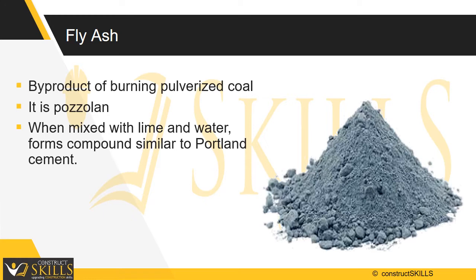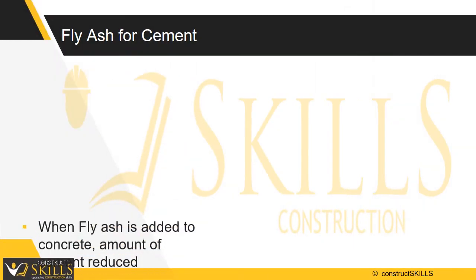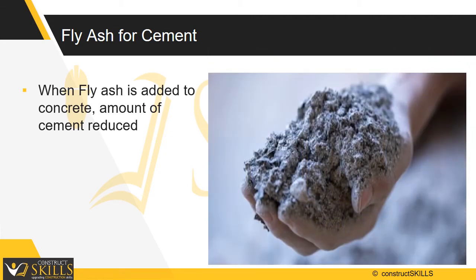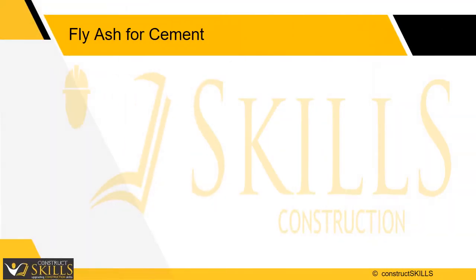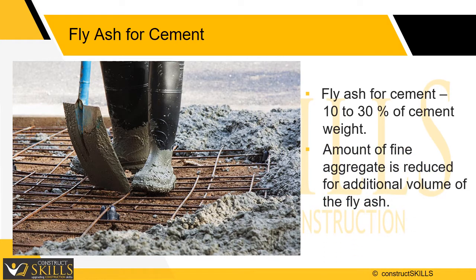The use of fly ash improves concrete performance in both the fresh and hardened state. When used in concrete mixes, fly ash improves the strength and reduces segregation of the concrete and makes it easier to pump. When fly ash is added to concrete, the amount of cement may be reduced. The amount of replacement depends upon the design consultant. The rate of substitution of fly ash for cement is typically specified at 10 to 30 percent of total cement weight. Accordingly, the amount of fine aggregate in the concrete mix is reduced to accommodate the additional volume of the fly ash.